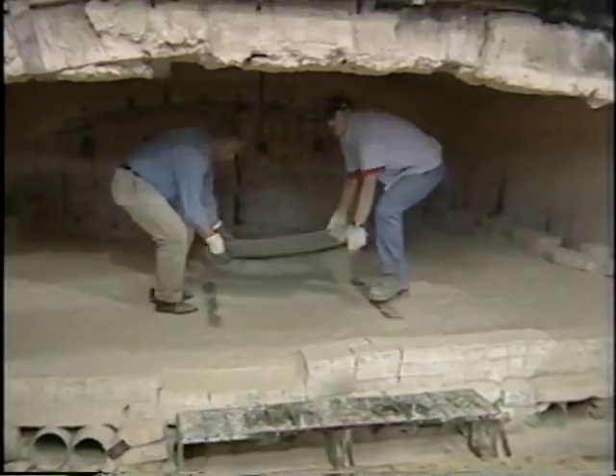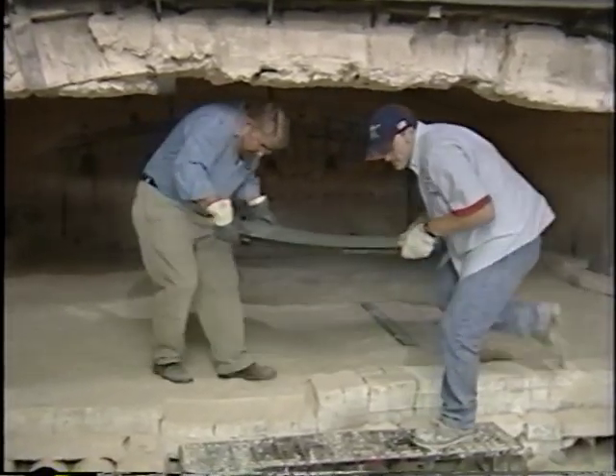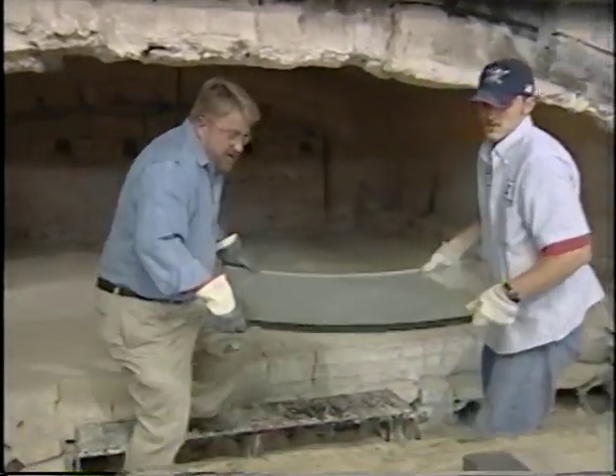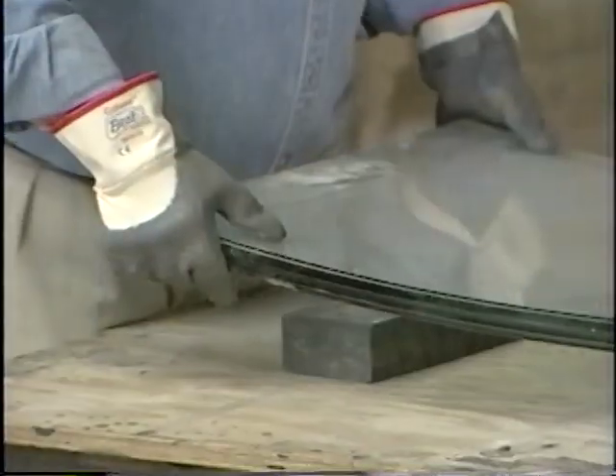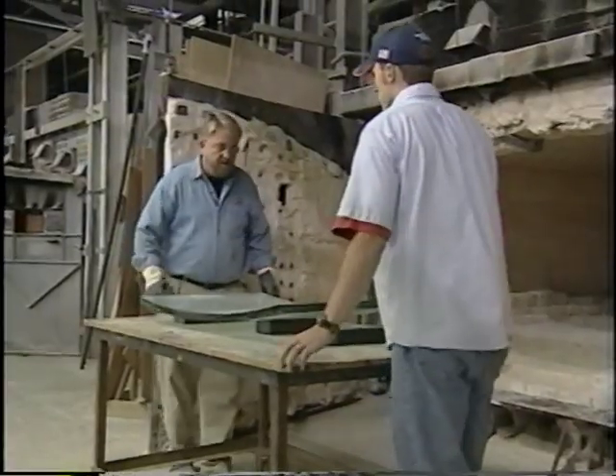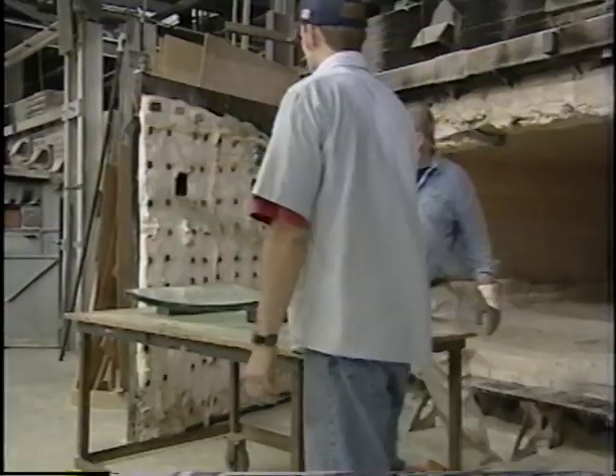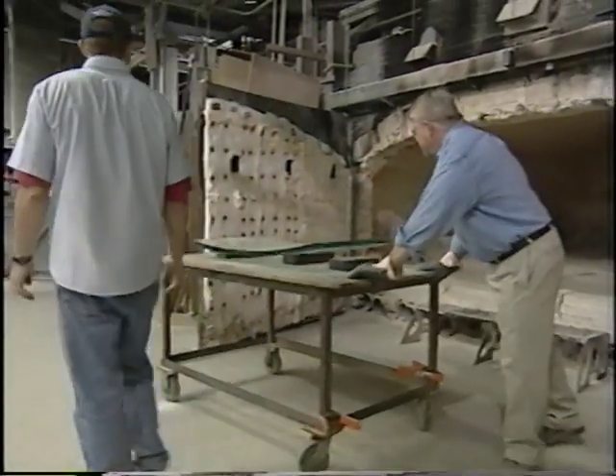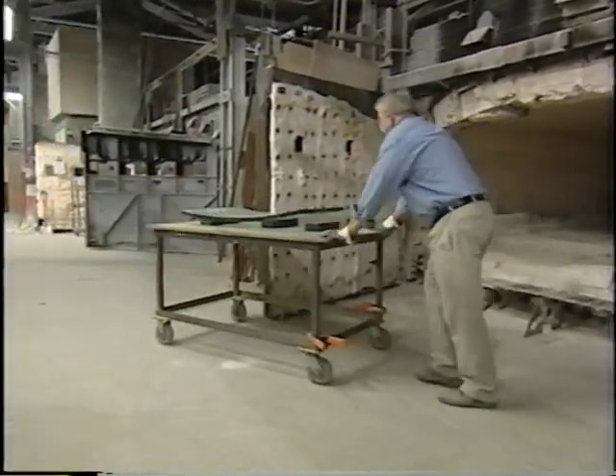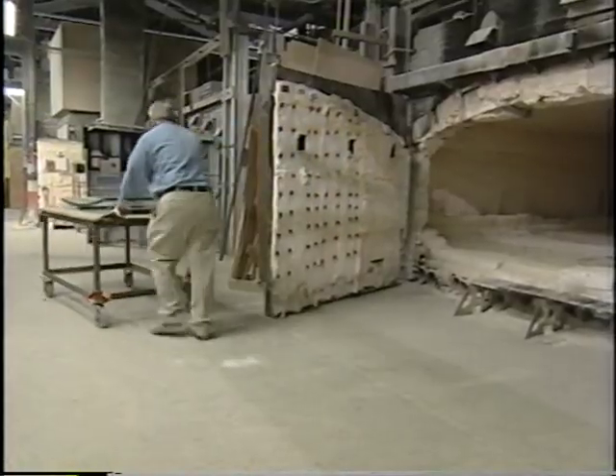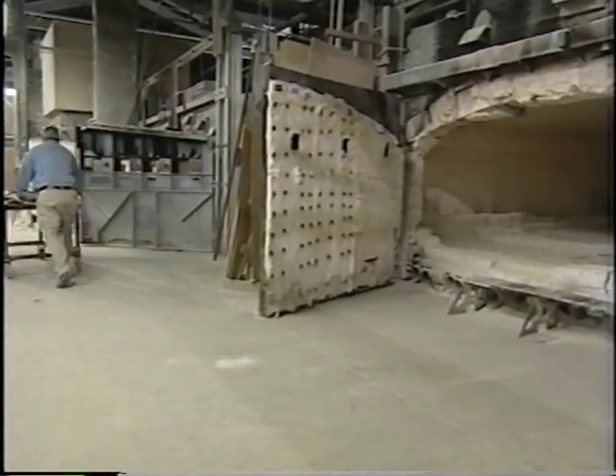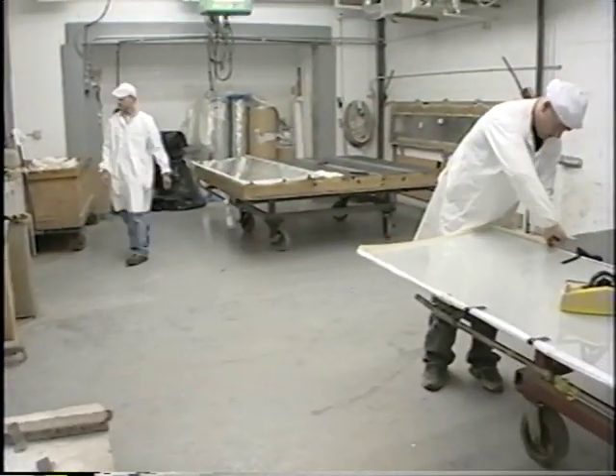My 4 sheets of glass spent 2 hours in the furnace at 1200 degrees and then cooled for 7 hours. There we go. All right, Ron, it's ready to go to Lammy. Okay, down this way? Yep, down that way, straight through the tunnel. Now the glass is ready to be laminated with the polycarbonate. In this case, we're going to layer it with sheets of PVB, a resin that glues layers of glass into a strong single sheet.